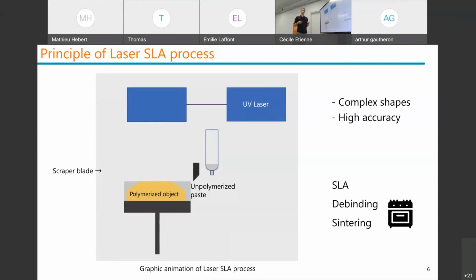The organic parts I have only serve to make the good shape I want, because after that, I will clean my parts, so remove the unpolymerized paste. And after that, I will put it in an oven for debinding, so removing all the organic parts, and then a sintering oven at very high temperature to densify and get very dense ceramic parts.